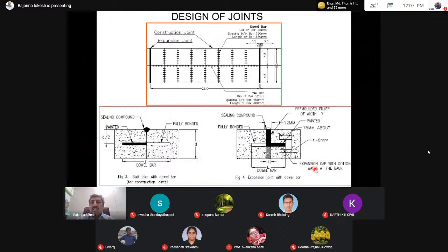And longitudinal joints are provided at every 3.5 meter with a tie bar. This is a typical section of the joint arrangement, where you can see this is the longitudinal joint with tie bars, and this is the transverse joint with dowel bars. Generally, the tie bars will be around 12 mm diameter, whereas dowel bars will be 25 or 32 mm diameter, which is once again dependent on the design, the pavement thickness.